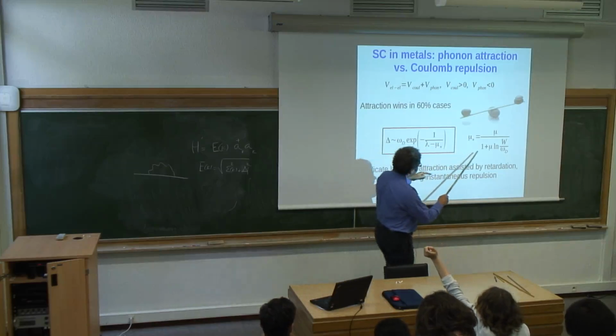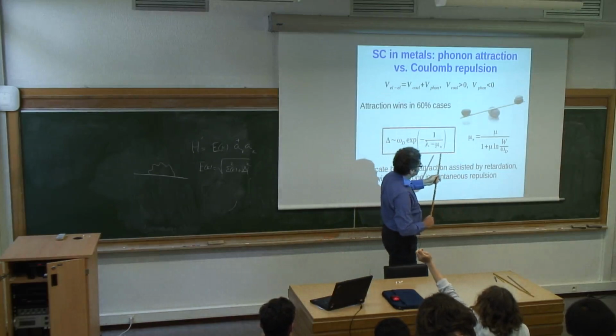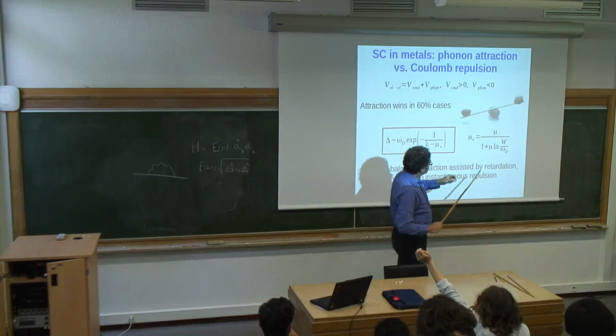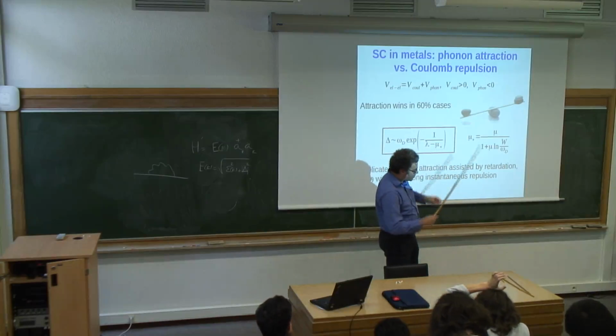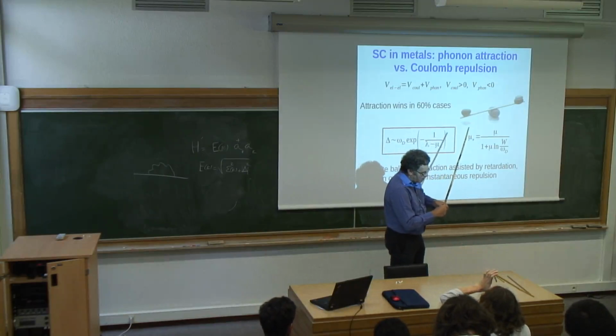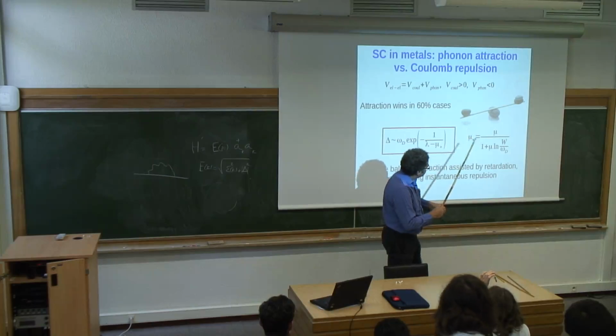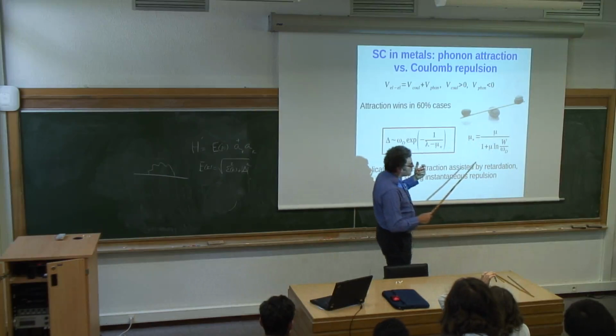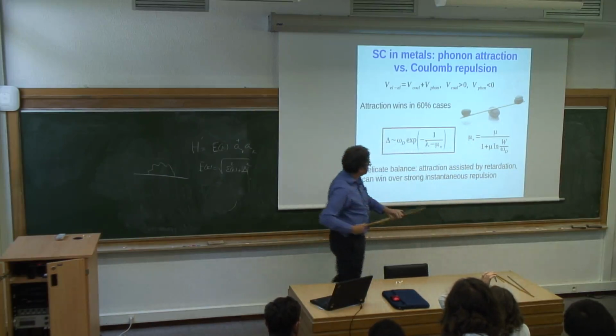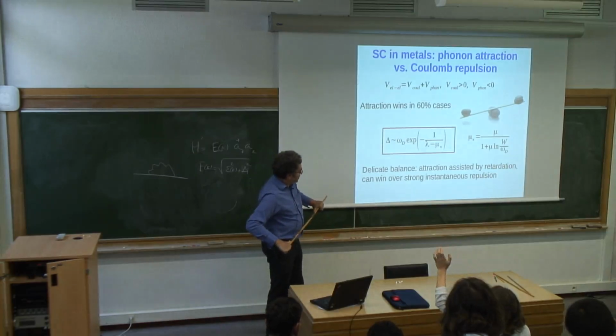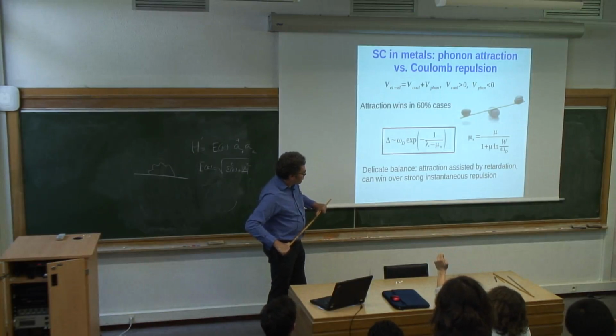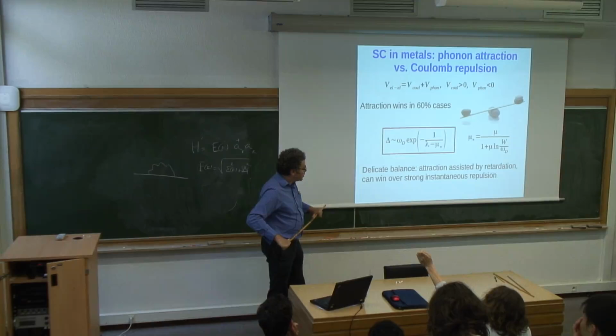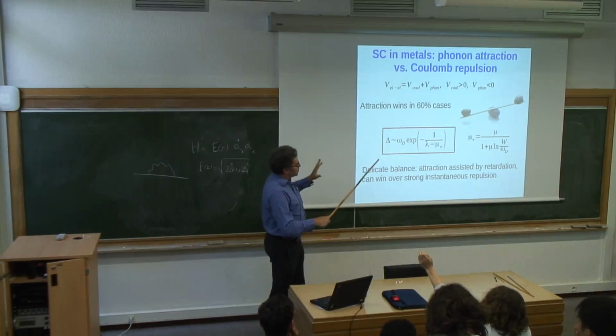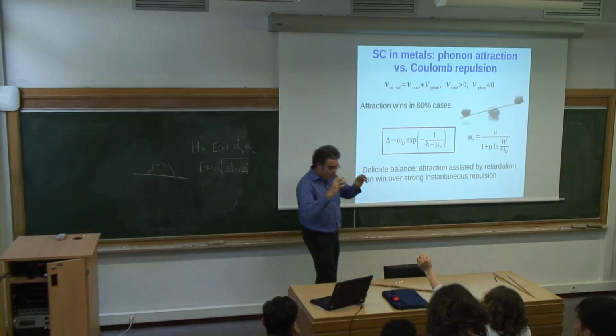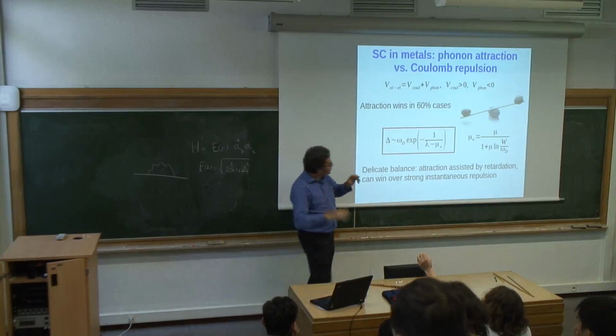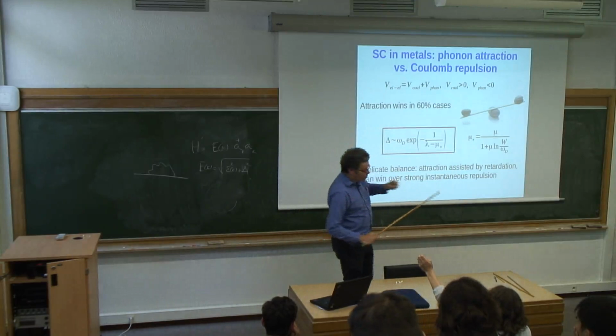However, the suppression is not too big because of this retardation effect diminishing the effect of Coulomb repulsion, because particles which attract each other are typically far apart. You get a reduction in this Coulomb part by this log factor, and so this is the mathematical expression for how Coulomb repulsion, even though it's nominally stronger, cannot win over phonon attraction. However, from this picture you see that there is always a delicate balance of forces, and it's only because of that retardation effect that phonons can win.